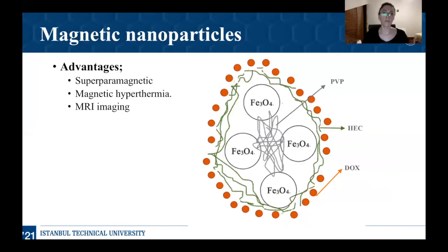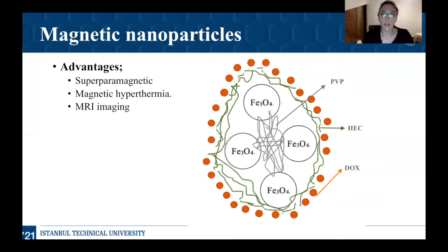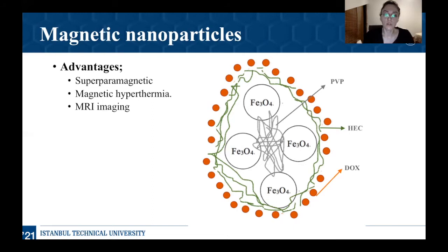We produced two different types of chemoembolization particles. One is produced using magnetic nanoparticles and the other one using clay particles. Magnetic particles can be heated under alternating magnetic fields, which can induce magnetic hyperthermia at the tumor site. It is a known fact that increasing the temperature at the tumor site increases the efficacy of the tumor drug, and also higher temperatures damage the tumor tissue itself.